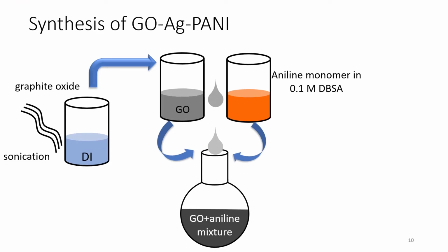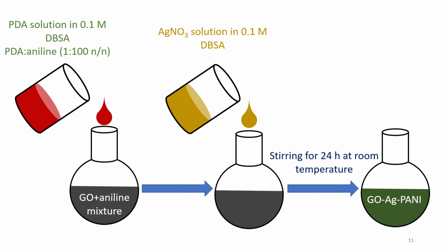So in the synthesis we first took graphite oxide into deionized water and sonicated to obtain graphene oxide, and mixed it with the aniline monomer. After that we added phenylenediamine solution and finally silver nitrate solution, and stirred the mixture for 24 hours at room temperature to obtain graphene oxide silver polyaniline.